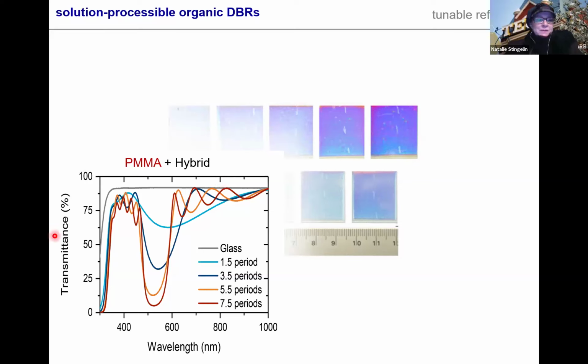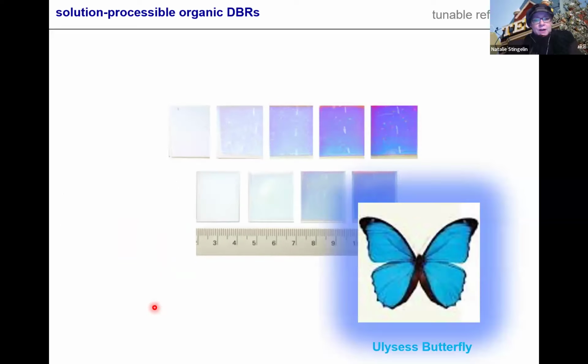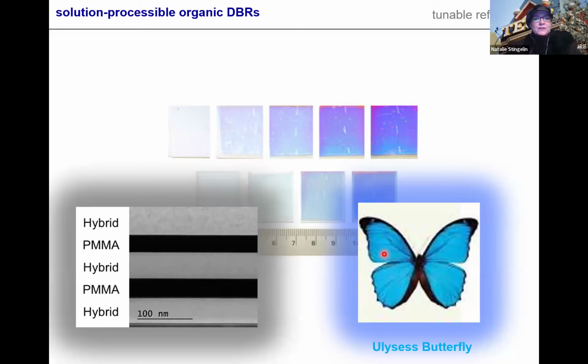So these are experiments where you measure the transmittance. You see the more layers you have—one period means one low and one high refractive index layer—you start to build up what physicists call a stop band. So you start to reflect the light of lambda divided by 4. And this is often used in nature. For instance, this butterfly in Australia that looks blue, they have these photonic structures on there.